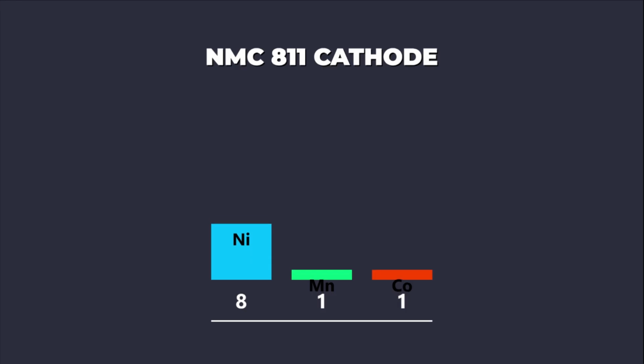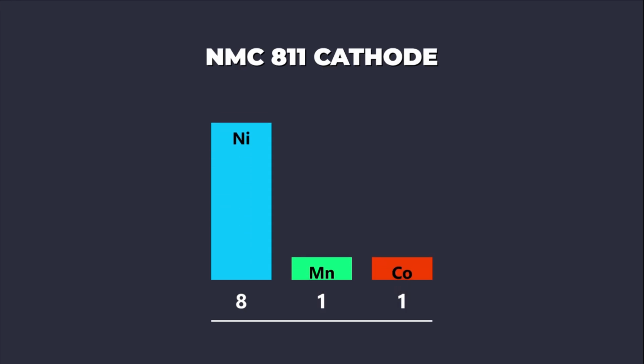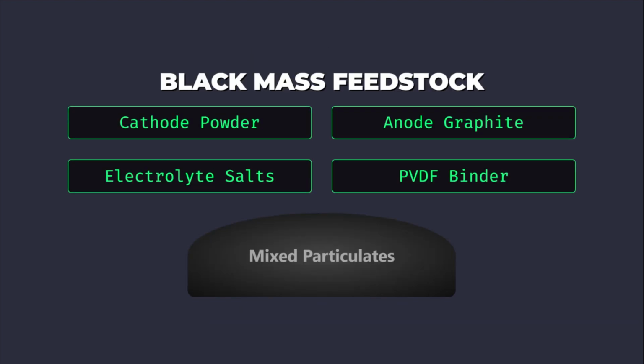adoption. The challenge is separating the complex layered oxide structures, such as NMC 811, where nickel content is 8 times that of cobalt. The black mass, a mixture of cathode and anode materials, electrolyte salts, and binder, is the primary feedstock for chemical recovery processes.